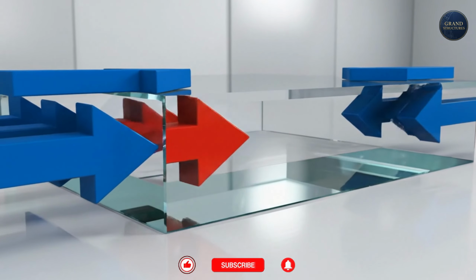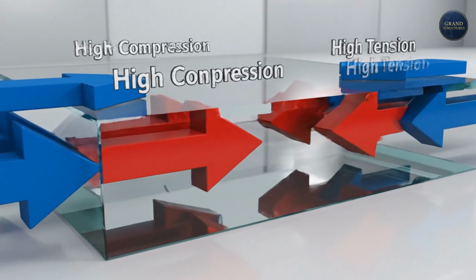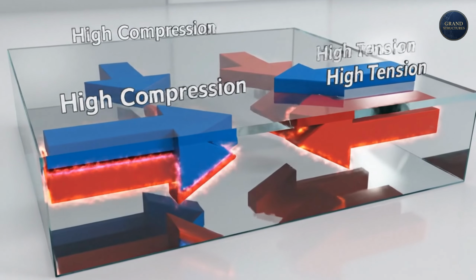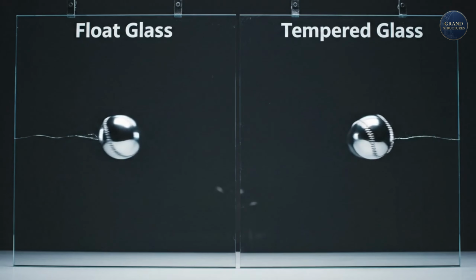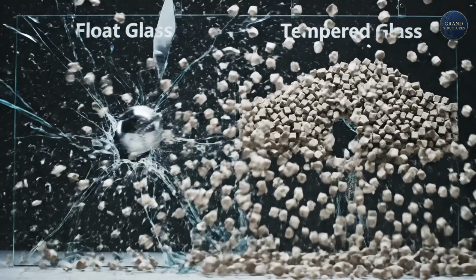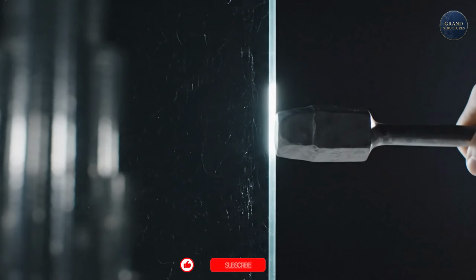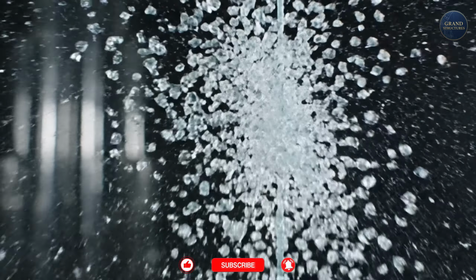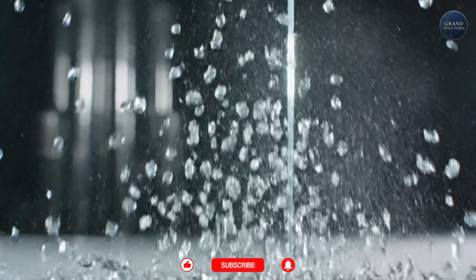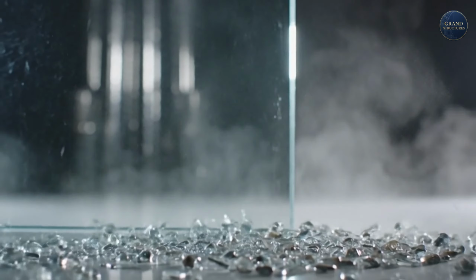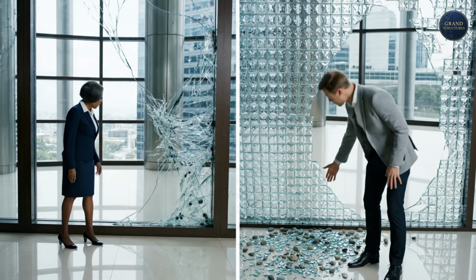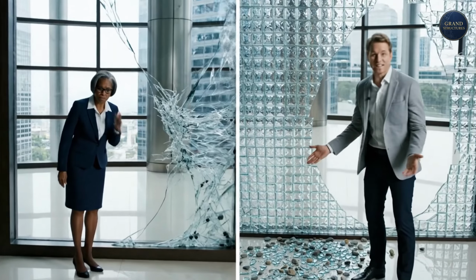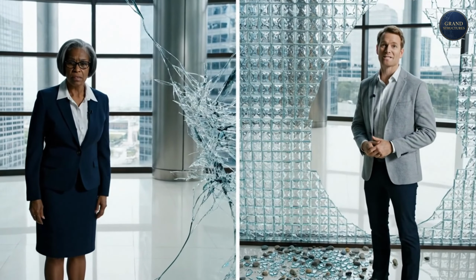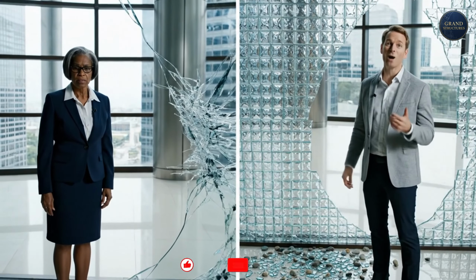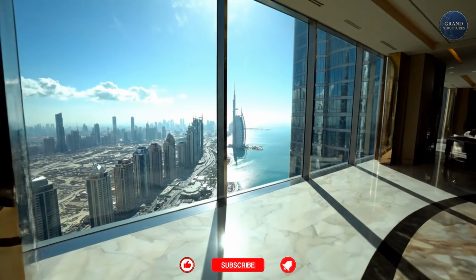The outer surfaces are locked in a state of high compression, while the inner core is in tension. These opposing forces are what give tempered glass its incredible strength. It's now 4 to 5 times stronger than the original float glass. And as a bonus, if it does break, it doesn't create sharp, dangerous shards. The stored-up energy causes it to shatter into thousands of small, safe, pebble-like crumbs, a critical safety feature for a